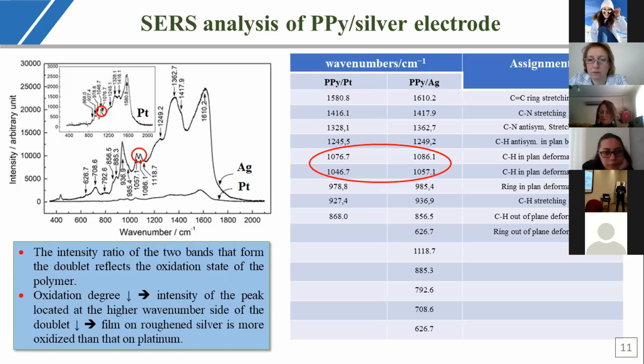The intensity ratio of the 2 bands that form the doublet of C-H in-plane deformation reflects the oxidation state of the polymer. Others stated that when the oxidation degree decreased, the intensity of the peak located at the higher wave number side of the doublet decreased and almost disappeared. In our case, by comparing the intensity of these 2 bands in the spectra of the 2 systems, it appears that the film elaborated on roughened silver is more oxidized than that on platinum.